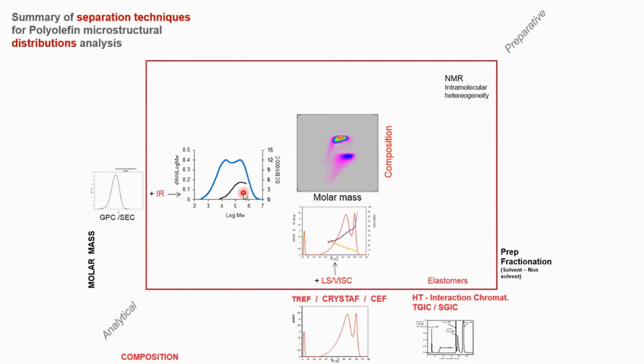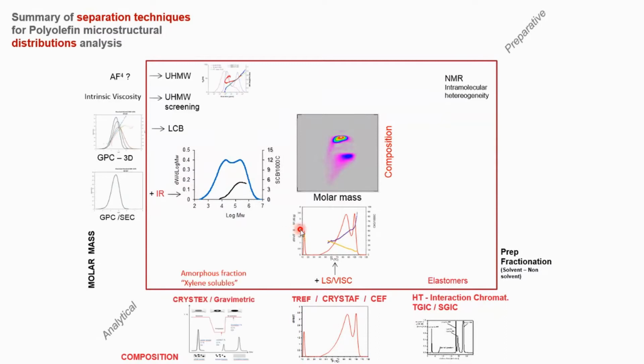When adding complementary detectors, GPC with infrared or TREF with light scattering and viscometer, useful information in the interrelation of the two dimensions, chemical composition and molar mass, is gained. Some other specific techniques, such as triple detector GPC, AF4, intrinsic viscosity analysis, or also the solubles analysis by gravimetric method or automated CRYSTEX, have been developed for special applications.